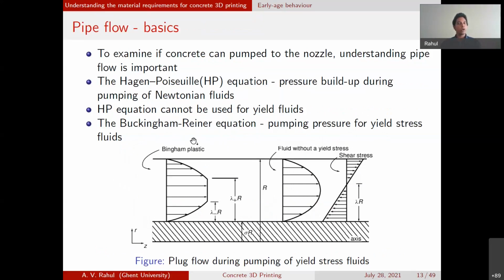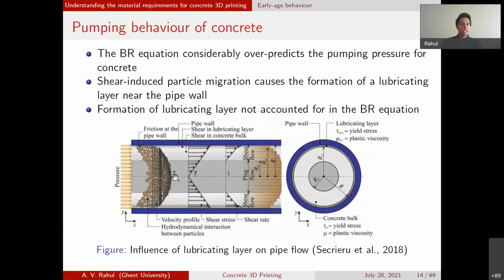But if you do it with concrete, you will see that the Buckingham-Reiner equation gives a much higher value than what is experimentally observed. Say, for example, if you measure the pressure as 10 bar experimentally with concrete, when you substitute in this equation, you might get values as high as 30 or 40 bar, several times higher. The reason why this happens is because the Buckingham-Reiner equation doesn't consider the formation of a lubricating layer that happens in the case of suspensions like concrete.